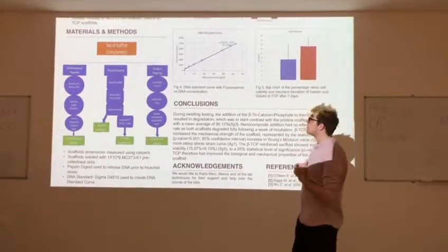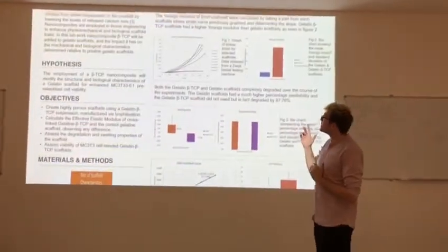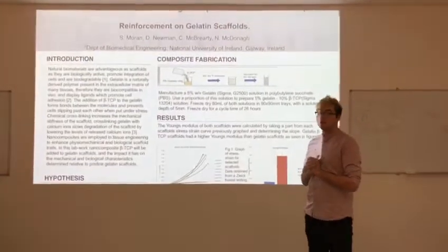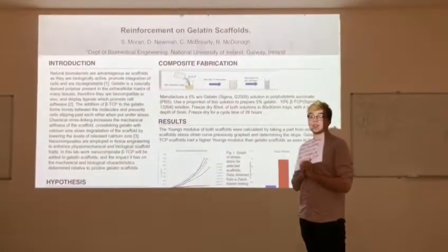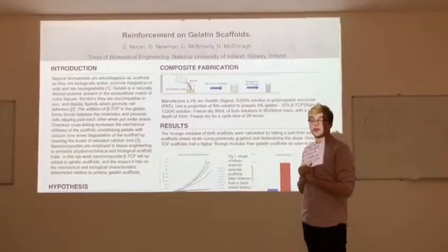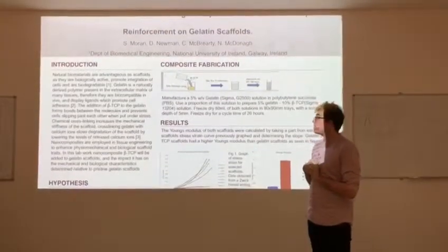So we fabricated the composite by creating a 5% gelatin, 10% beta TCP solution in PBS and freeze drying it for a 26-hour period.